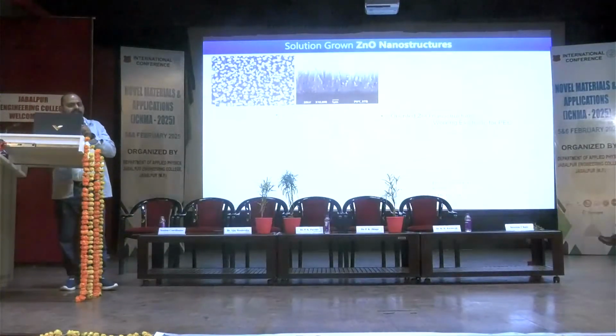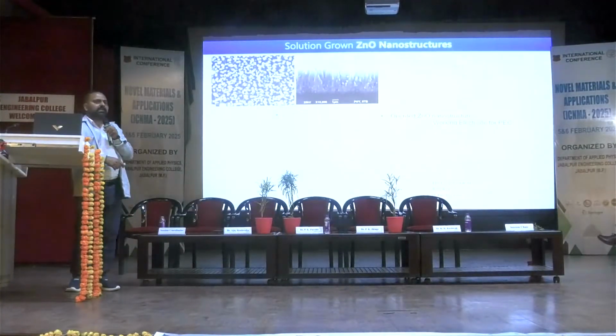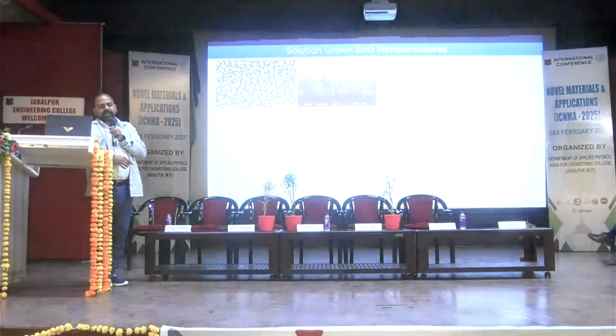What was the issue? The material has a wide band gap, and is only able to harvest some of the solar light, because the solar energy lies almost 5% in UV, less than 50% in visible, and then infrared. And this material is only sensitive to UV light. So when you are not able to harvest the light, how do you utilize it? That is one challenge, so we needed some kind of modification.